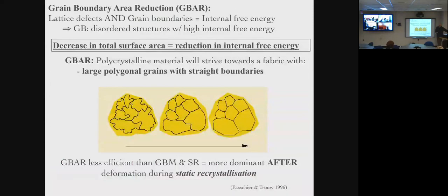Finally, there is one other texture that will operate with diffusion, but in the absence of strain. Okay? This is called G-bar, or grain boundary area reduction. This is the beer foam texture, right? So if you have a grain that shows beautiful grain boundary migration texture, such as this, a high temperature deformation fabric produced by heat and strain, and the heat persists in the absence of strain, notice how these grain boundaries become much straighter, and the grains then join up in a triple point stable configuration.